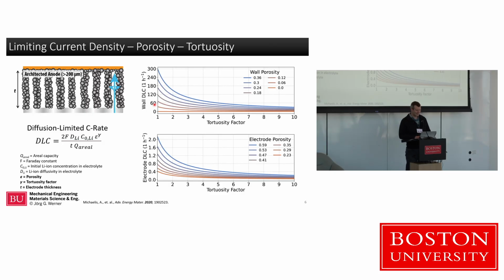So this seems to indicate that if you're getting down to 10 or 20 micrometers, a C rate of 60 would be a 1-minute charge. Everyone would be happy. So it sounds like these very thin layers, if it was a thin layer as a single layer in your battery, would be really fast, but you wouldn't store much energy. But if we architect it like that, the thin layer may not matter as much. It's really just the electrode level, the 100 to 200 micrometer thickness that we have to worry about.